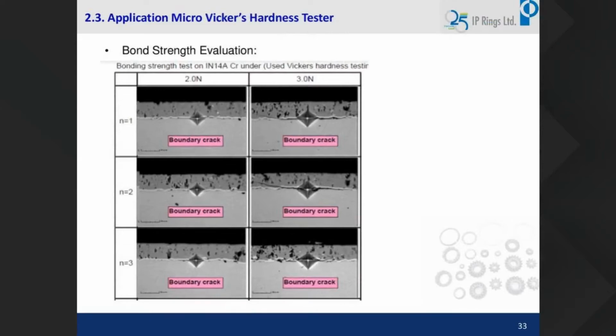Then this is bond strength. Just now you saw the pictures, but I have a case study which I'll explain at the end of the session. In bond strength, this is the substrate material and this is the coating. In between there's a thin line which is pure chromium coating. If you put an indentation, there should not be any crack running like this. If there is a crack, the bond is not intact, which we call a boundary crack.